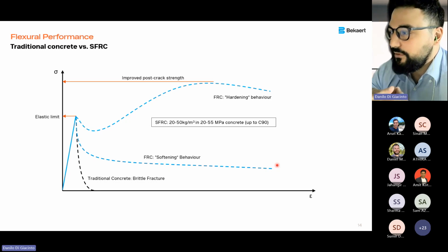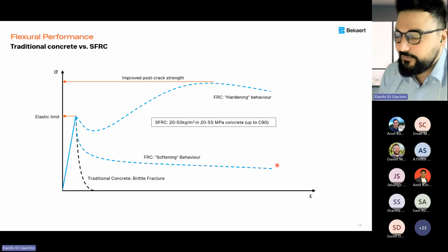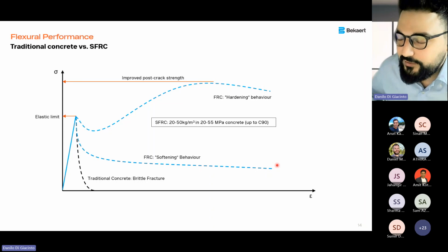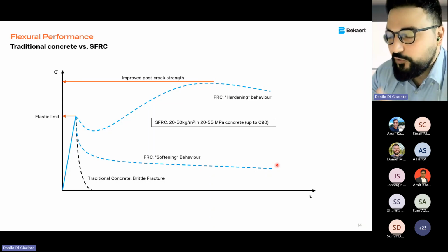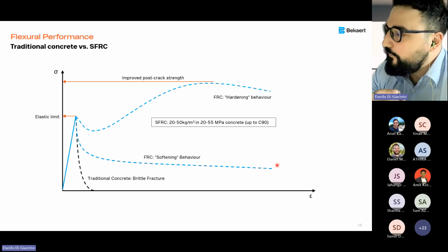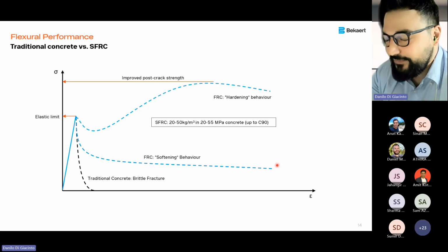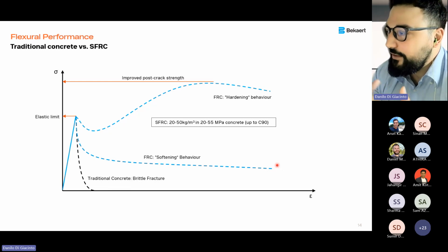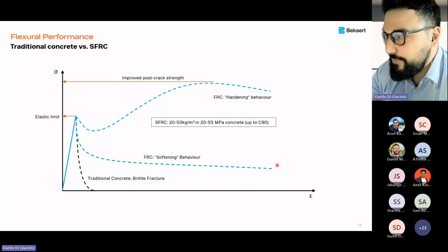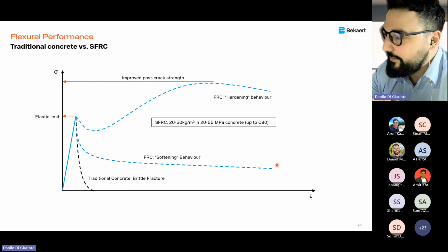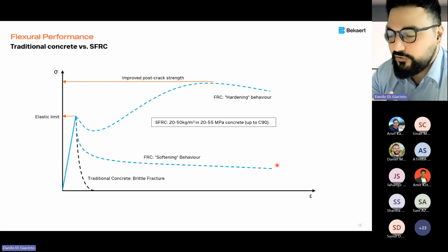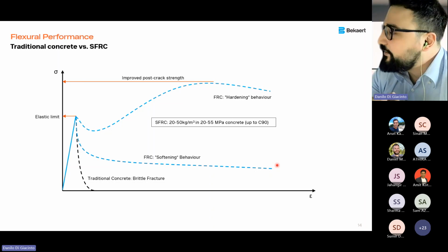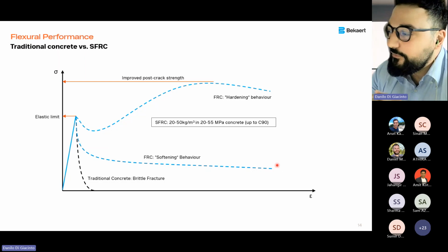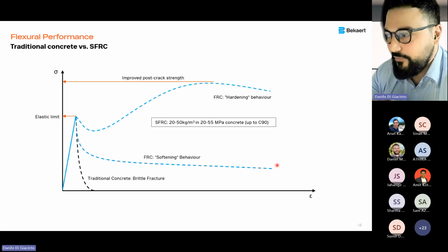With SFRC, a typical, standard SFRC, consider a dosage between 20 to 50 kg of fibers per cubic meter for concrete classes with compressive strength between 20 and 55 MPa, but it can go up to C90 for heavy duty structures, like for example, bridge girders. You can achieve either a softening behavior or a hardening behavior.